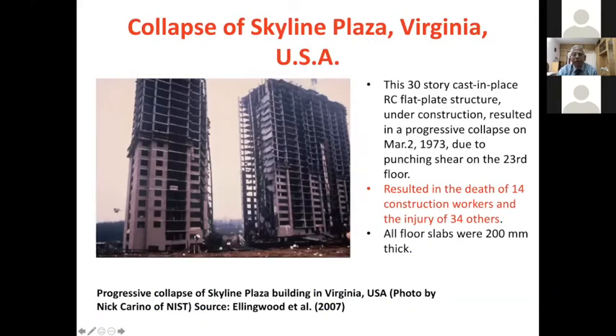Of course, failure of slabs are rare, especially in small buildings, but in high-rise buildings, especially using flat slab, you have to be very careful to support them properly. This is a failure which happened in Virginia, USA. This 30-story cast-in-place RC flat slab structure under construction resulted in the progressive collapse in March 1973 due to punching shear on the 23rd floor. It resulted in the death of 14 construction workers and the injury of 34 people. All floor slabs are 200 mm thick.